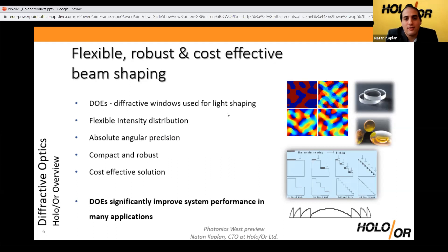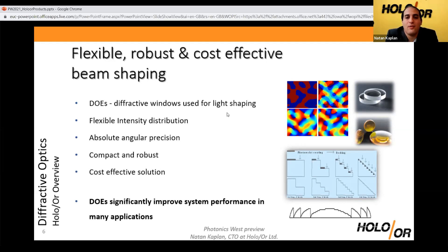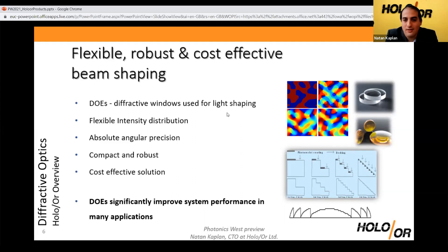So what are diffractive optics? Diffractive optics, or diffractive optical elements — which I will call DOEs — are basically thin light windows that can be used for the shaping of light. Our diffractive optics are based on phase relief gratings: etched structures into the raw material of the window, which is either high-grade UV fused silica or zinc selenide for longer wavelengths. These structures are etched and create a controlled phase profile on the wavefront of the laser.